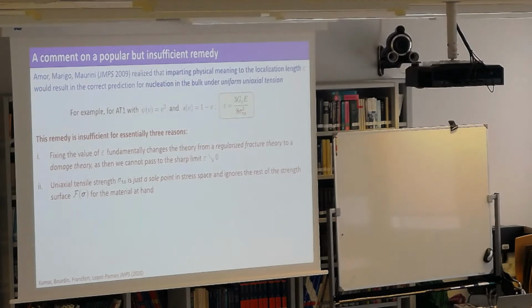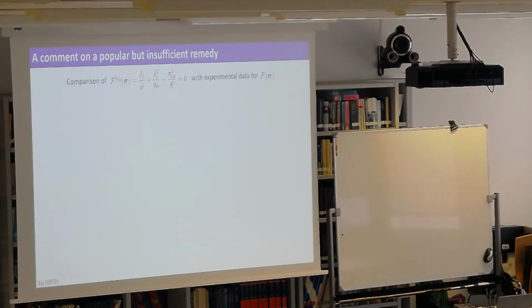If you only use the tensile strength, this is just one point in the entire strength surface, right? So as I said, from experiments we know that we might have an entire strength surface, not just the point in uniaxial tension. And again, when you fix epsilon, you get actually an entire strength surface that has been fitted to uniaxial tension. That is the formula, and then you can plot the formula and compare with experiments. But again, this is not surprising, right? Because you're calibrating things with tension, but there are other directions that are not calibrated, right? Okay? So, but again, somehow, this is telling us something very, very important.